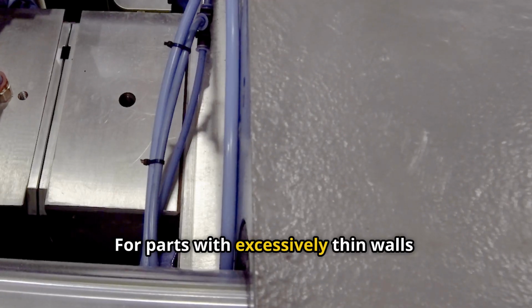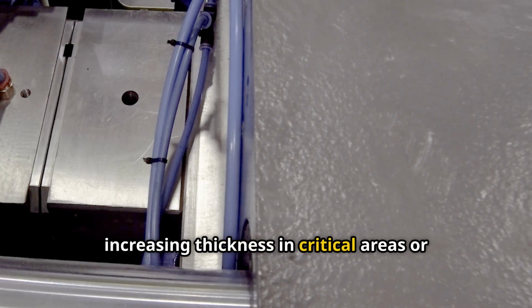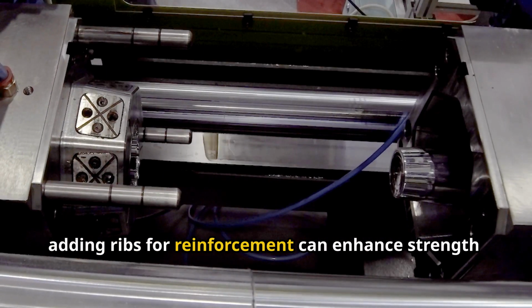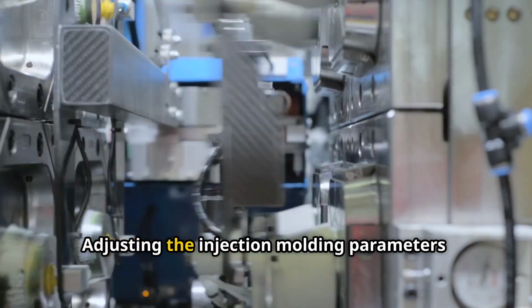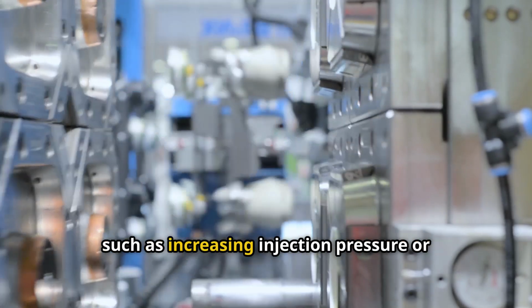For parts with excessively thin walls, increasing thickness in critical areas or adding ribs for reinforcement can enhance strength. Adjusting the injection molding parameters, such as increasing injection pressure or melt temperature, can also mitigate issues like short shots.